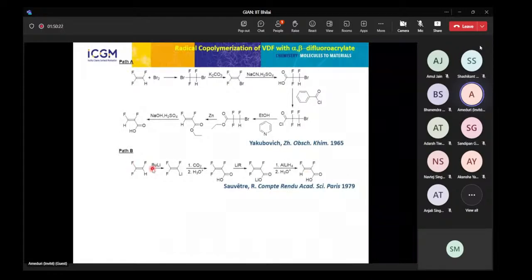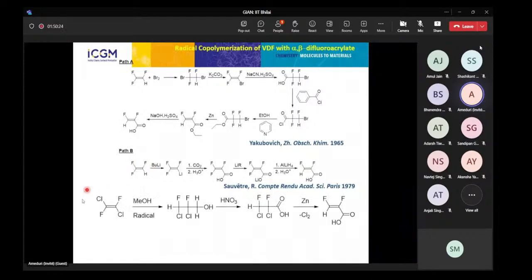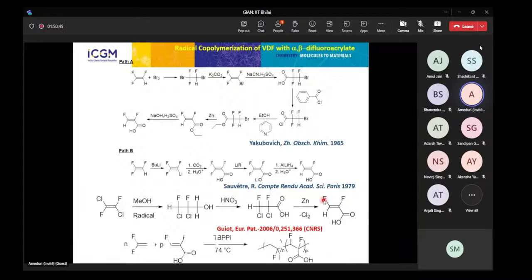But we decided to go another way. We started from difluoroethylene, radical addition of methanol, in order to have this alcohol, then to oxidize this CH2OH to make the carboxylic acid, and then by dechlorination with zinc to prepare this alpha-beta difluoroacrylate. So this was good, and we decided to have a patent on that, a CNRS patent, and this was also more interesting because this monomer could copolymerize with VDF.